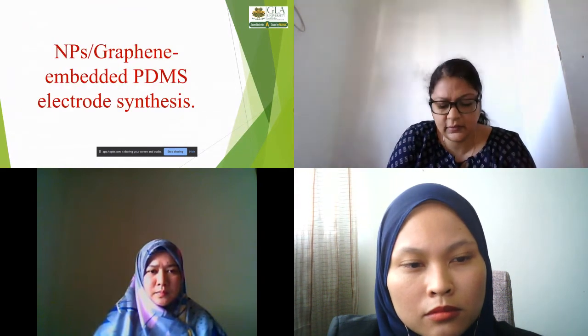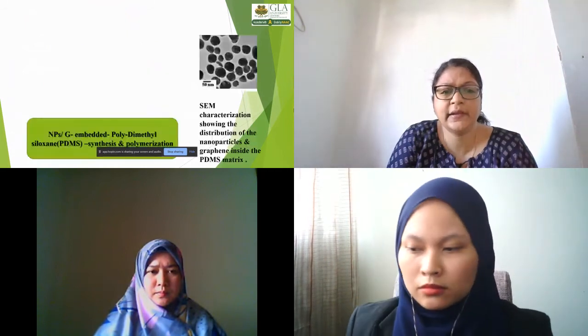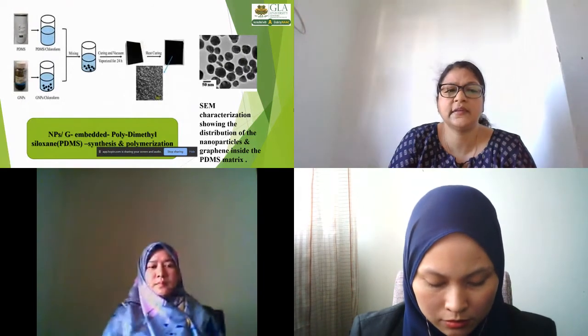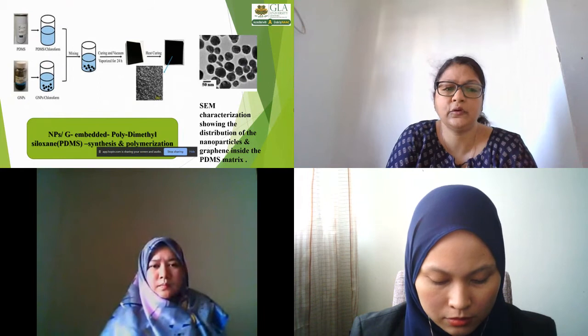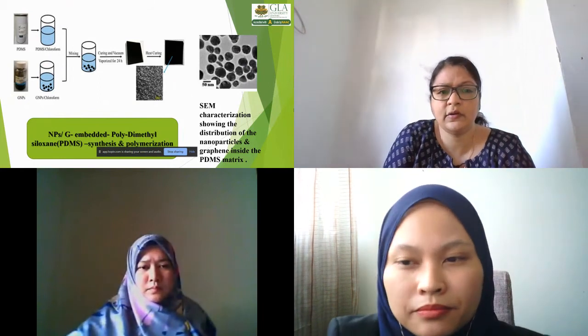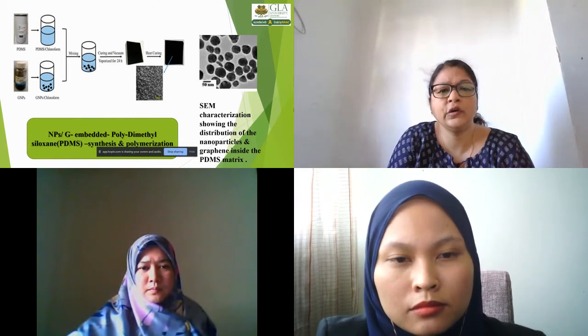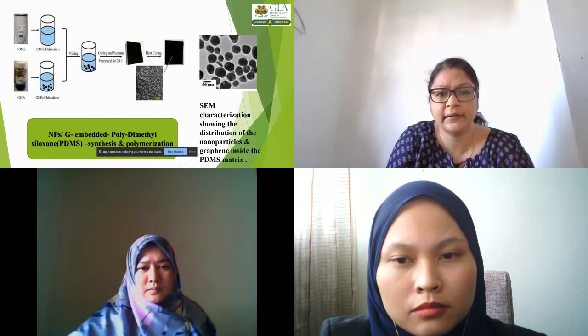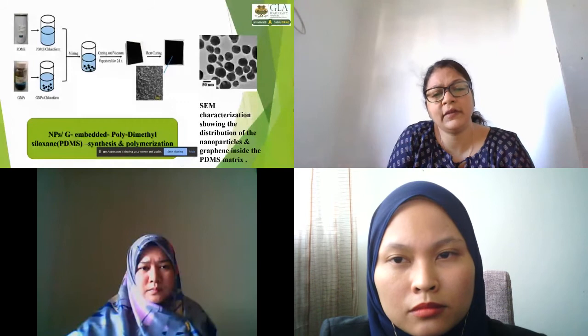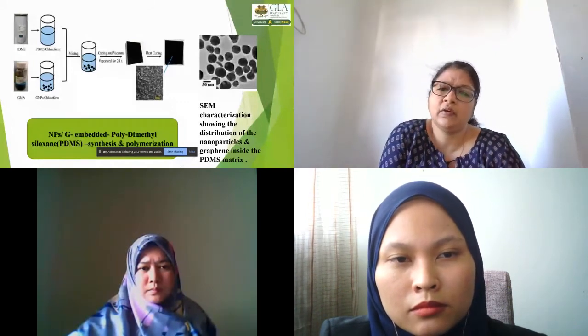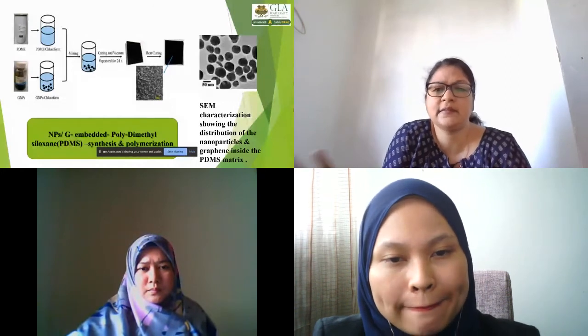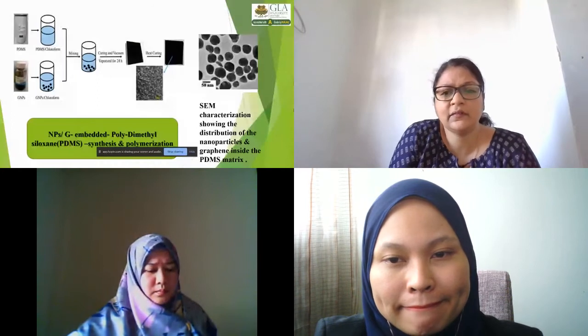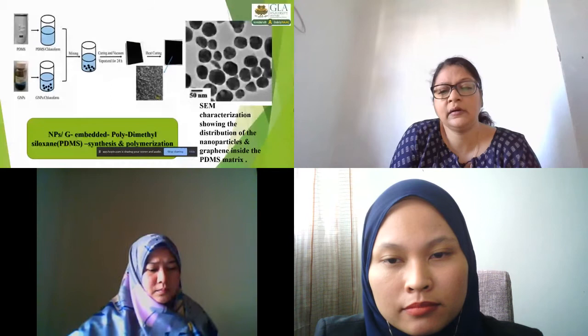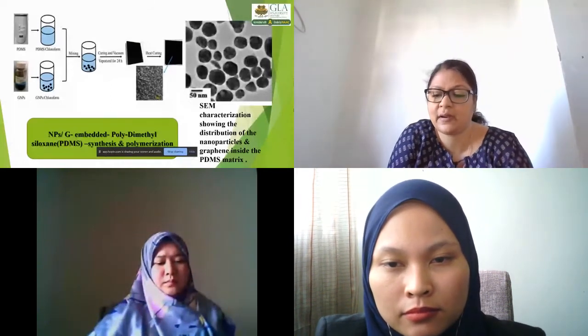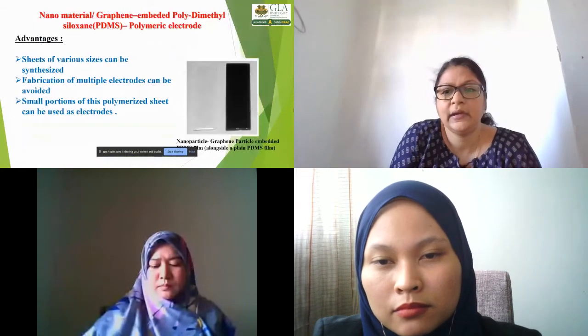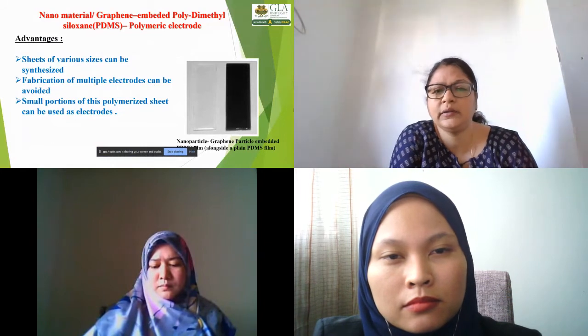For the synthesis of this polymeric electrode, we mixed the PDMS in chloroform, as it's highly miscible in chloroform. We also mixed graphene in chloroform, vigorously mixed it, and cured it on a glass plate. It was then vacuum evaporated and heat cured at around 150 to 200 degrees Celsius to form the polymer. The characterization of this polymer was done using SEM to see the distribution of the nanoparticles and graphene inside its matrix, and it was seen that it was beautifully, uniformly spread throughout. So this is how the polymer is made.